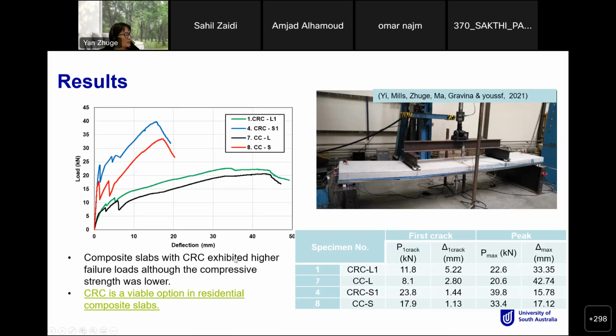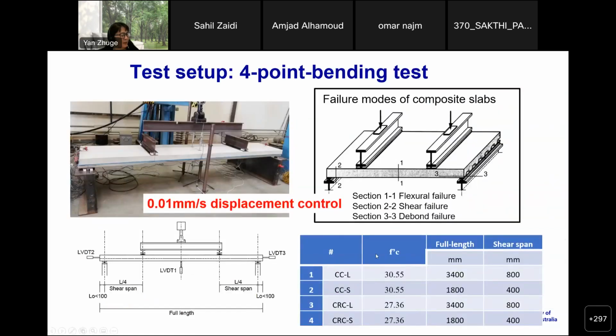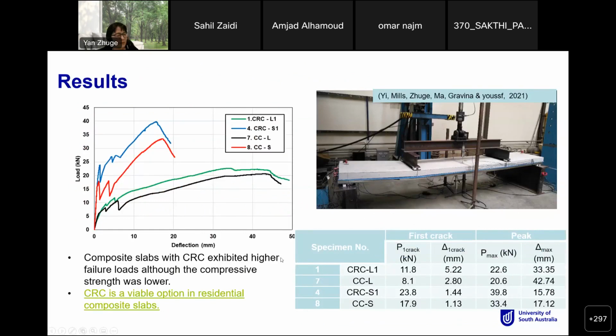Very interesting results. We can see the composite slab with crumb rubber concrete had higher failure load, although the compressive strength was lower. That's my point, which I talked to you about at the beginning of my presentation. I didn't show the compressive result here, but it's in our paper. When using 20% crumb rubber, there is more than 30% reduction in compressive strength, but this does not really affect the flexural strength at all.